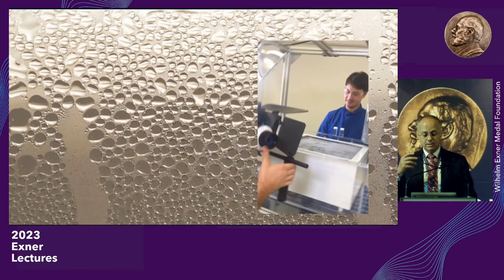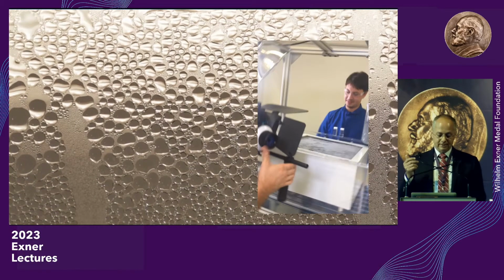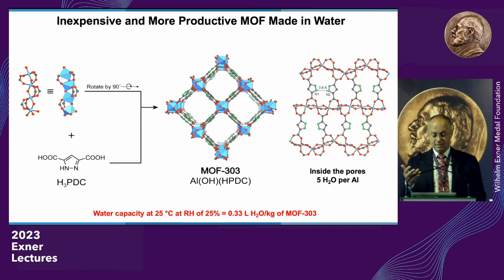Okay, so that was a zirconium MOF. And the nice thing about reticular chemistry is that if you have a metal like zirconium, which is expensive, like $170 or $160 a kilo, you could go to aluminum and make a much cheaper material. And so we made this MOF. I won't describe its structure, but just show you that if you're a molecule floating in the pore of the MOF and you look around the pore, you're going to see a hydrophilic pocket and a hydrophobic pocket. This is exactly the construct on the back of that beetle. There's a hydrophobic, hydrophilic, hydrophobic, hydrophilic, and Avogadro's number of these pockets throughout the material.